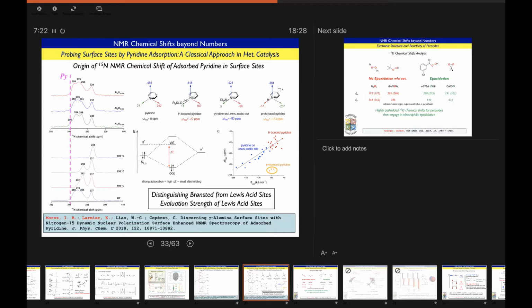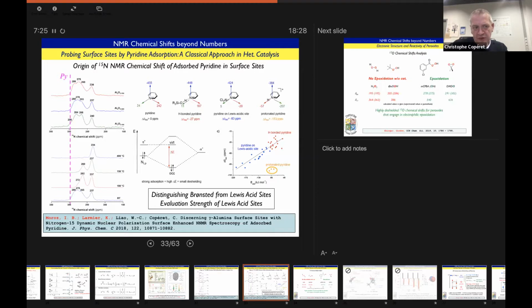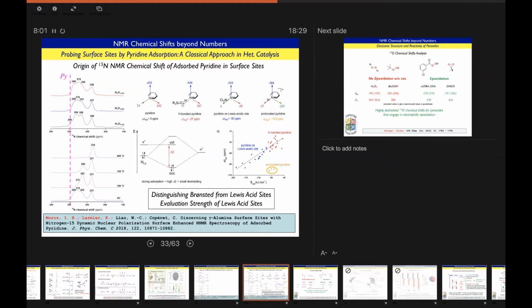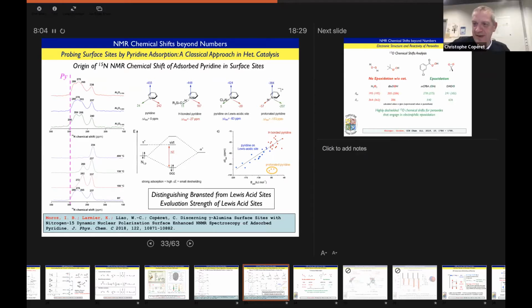It's also important to work at low temperature, because if you want to measure CSA, we should never overlook dynamics, since dynamics can average your CSA. So we always try to look at variable temperature experiments to measure the CSA. 100 Kelvin so far has been a nice temperature, because we can freeze most of the dynamics. But as in the earlier question, if we take a methyl group, it rotates, so we cannot freeze it. We would have to do DNP maybe at helium temperature, and then we may be able to see this pi interaction. Maybe a nice project to do with people who do helium-temperature NMR DNP.